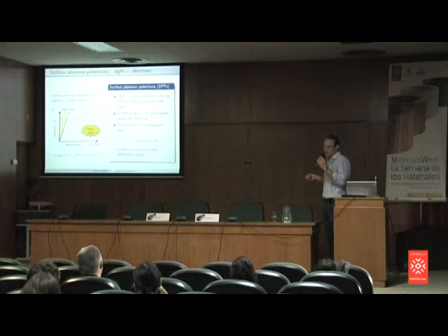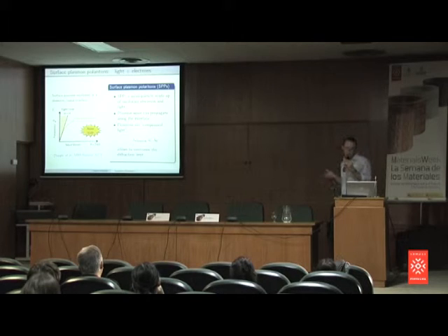So visible light has a wavelength of, let's say, order of magnitude a micron, no? Half a micron, okay? And we are at the micrometer scale. And at the same frequency, a plasmon is at the nanoscale. So we can just imagine plasmons as compressed light. Plasmonics is a means of making light small. And this is the most important feature of plasmonics, because this allows us to beat the diffraction limit, which limits classical optics, no? Because in classical optics, you can't make things smaller than half the wavelength. And in plasmonics, you can.